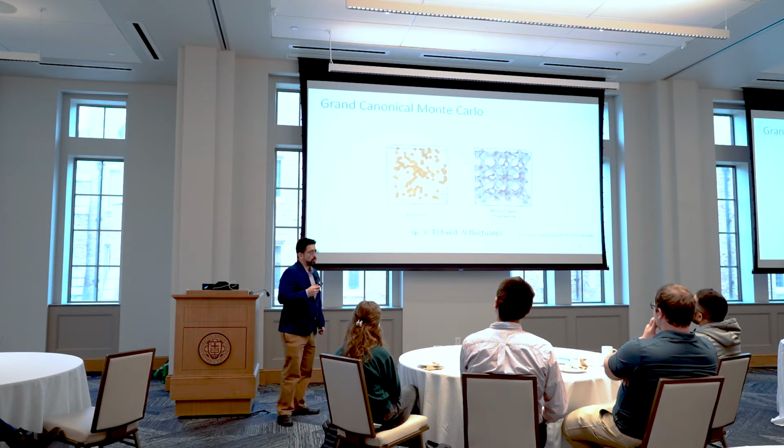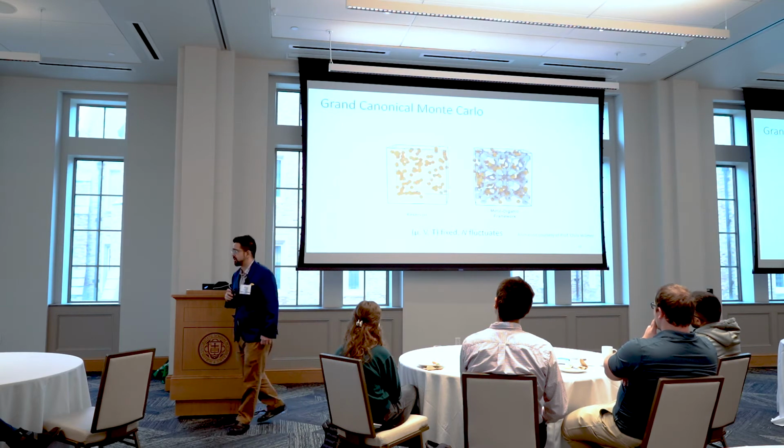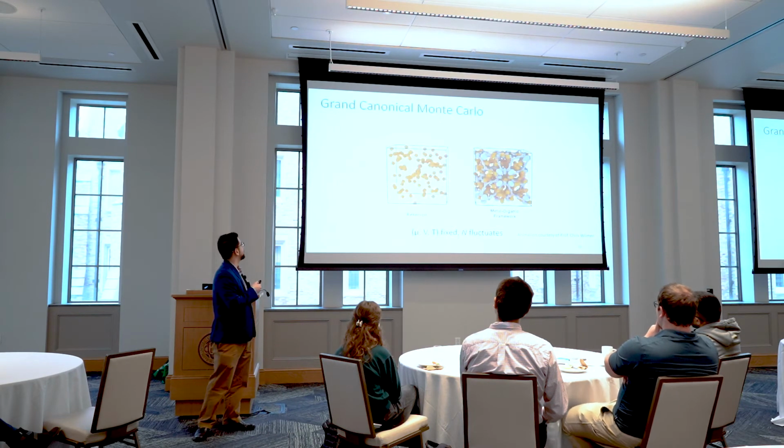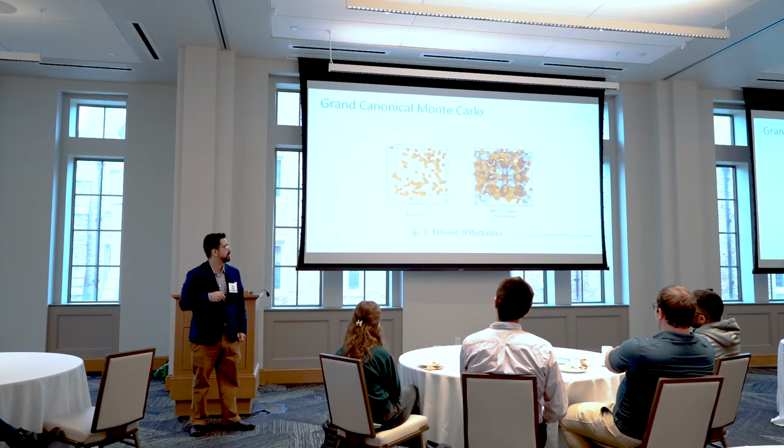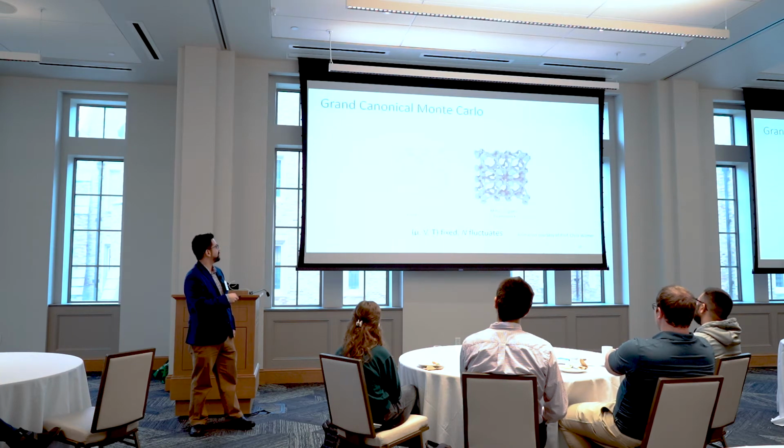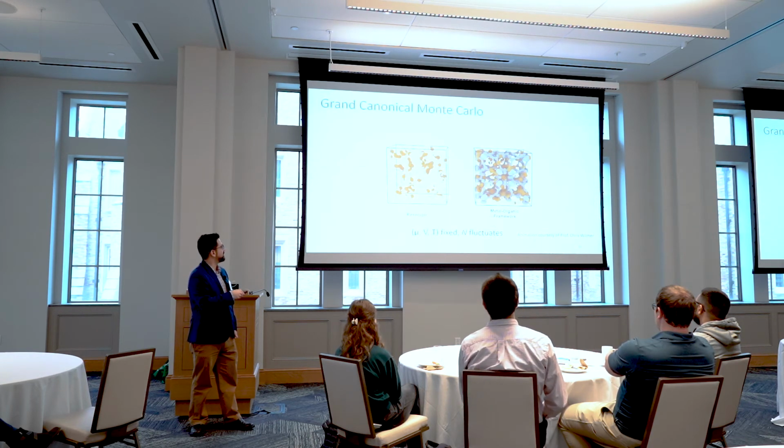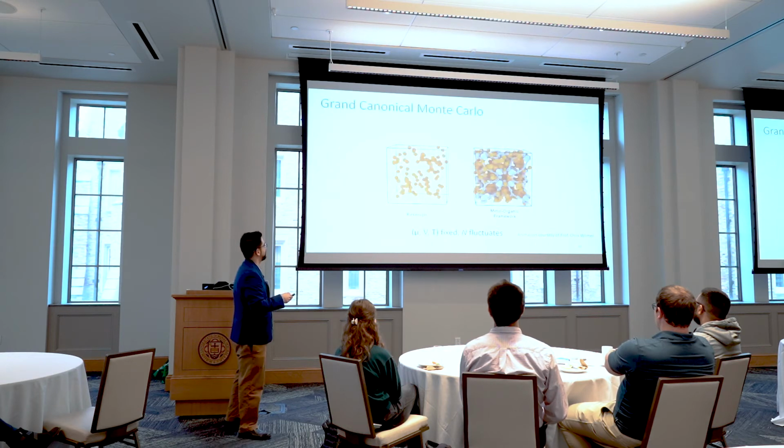Okay. Our workhorse is Grand Canonical Monte Carlo simulations. Grand Canonical stands for a statistical mechanics ensemble, which means we fix chemical potential, volume, and temperature. And so the number of molecules is allowed to fluctuate, right? So I can put this material here in gray, my MOF, in equilibrium with a reservoir. And then once this converges, I can get how much absorption I have.